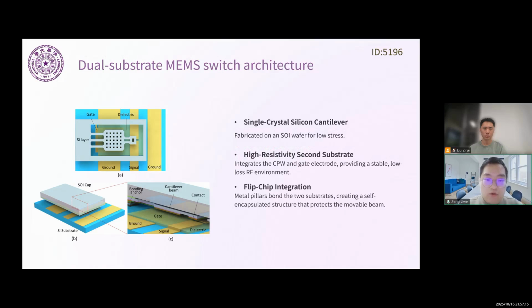On the first substrate, we fabricate a single crystal silicon cantilever on an SOI wafer. It gives us low stress, excellent mechanical properties, and high repeatability. On the second substrate, we use a high resistivity silicon wafer to build the RF environment, including coplanar waveguides, gate electrodes for actuation, and insulation layers. And to bring it all together, we use flip-chip bonding with metal pillars to connect the two substrates. The result is a self-encapsulated structure that protects the cantilever from the environment. So no need for extra packaging and no exposure to contaminants.